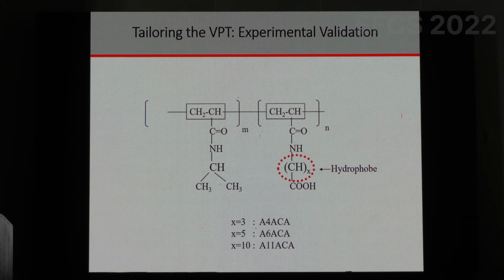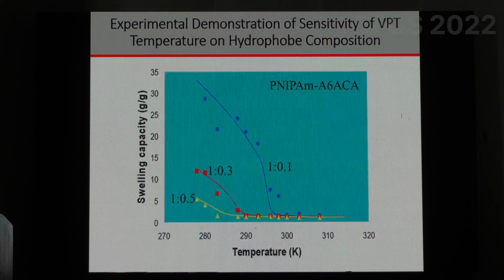So here is what we did. We took this N-isopropyl acrylamide and we copolymerized it with another molecule where I could vary the length of this spacer group, the CH2 group, right? And again, you can see that this is the hydrophobic part and these are the hydrophilic parts. Because I can change the length of this spacer, I can change the hydrophobicity, and maybe I can change the volume phase transition, and that's exactly what happens.